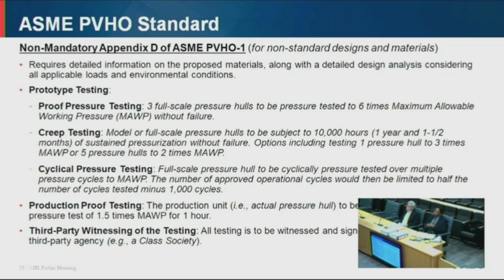Thereafter, you have to conduct prototype testing. This testing involves proof pressure testing. For this proof pressure testing, 3 full-scale pressure hulls are tested to 6 times maximum allowable working pressure, or MAWP, without failure. So this is basically a factor of safety test, okay? So you'll test the hull to 6 times its design pressure, and if it does not fail, that qualifies the design. The next testing is creep testing.